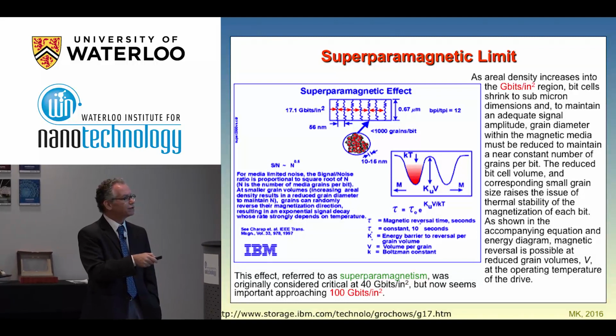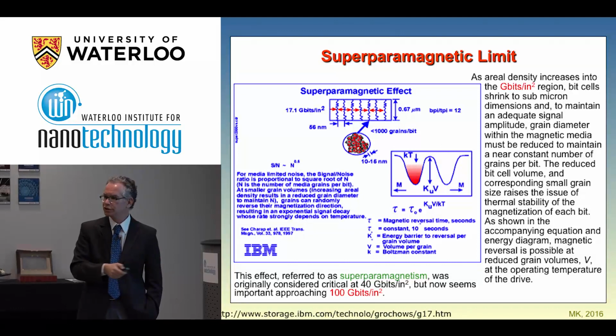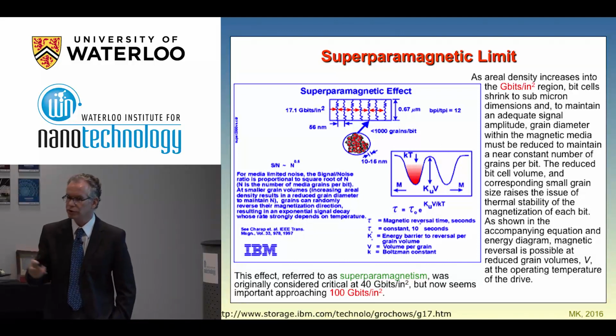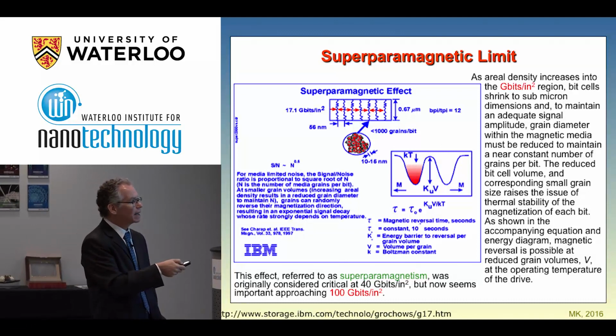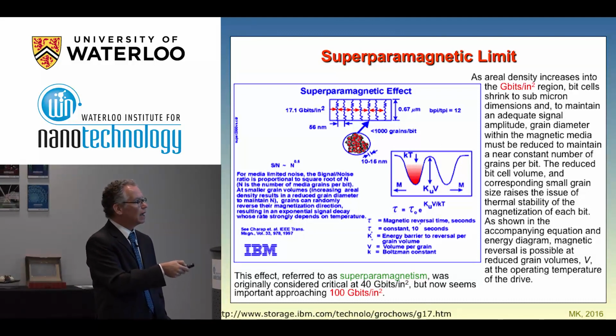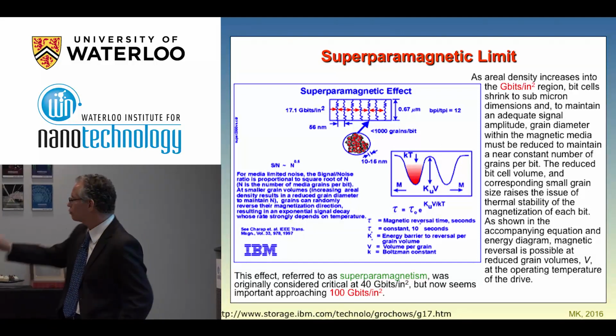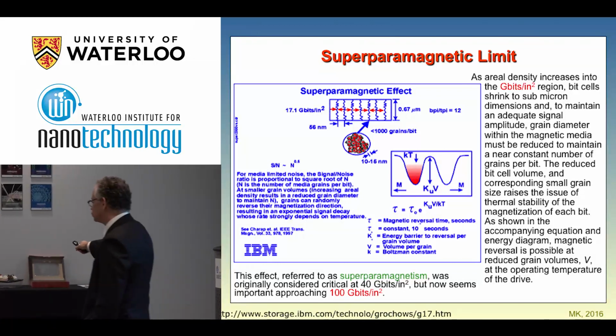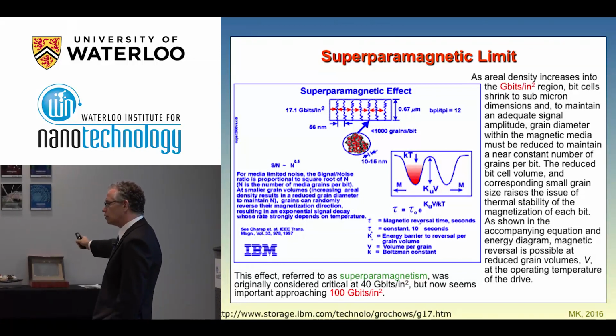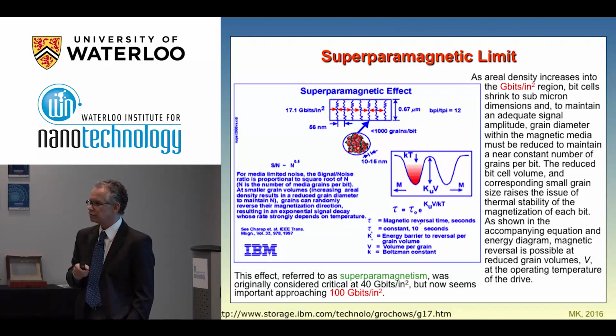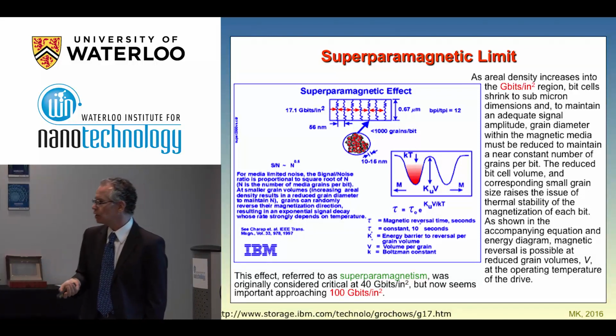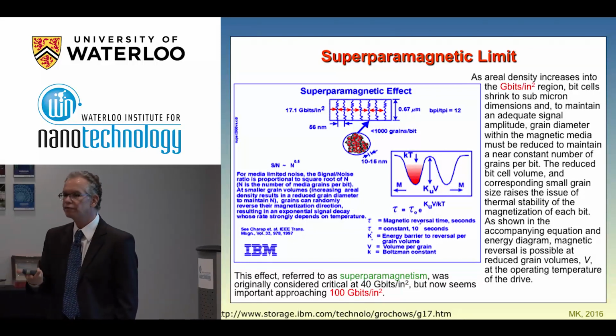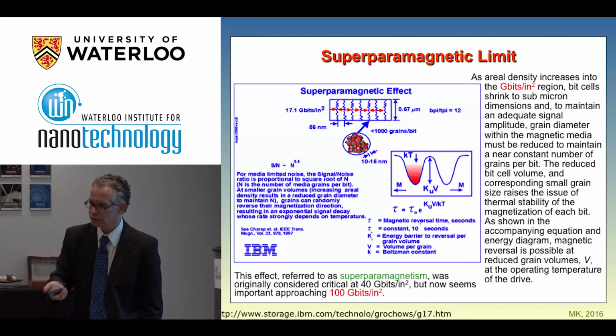and you reach a point where, when you reduce this barrier, the usual thermal energy becomes of the same magnitude as this barrier. And then if you record a zero, just by thermal fluctuations, thermal noise, you can jump to the other side. So essentially what happens is that you lose your information, which is not what you want.